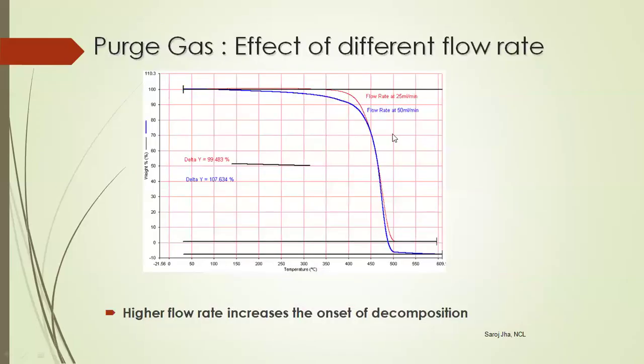This is very interesting and important for the research student, because you never know what flow rate the caretaker of the equipment has calibrated the instrument with. Here I have shown you that the instrument is calibrated at a flow rate of 25 ml per minute, and the student unknowingly ran his sample at 50 ml per minute, which is the blue curve. See, when the sample is run at the flow rate of calibration, that is 25 ml per minute, you get a proper degradation curve, which gives you residue as 0%.